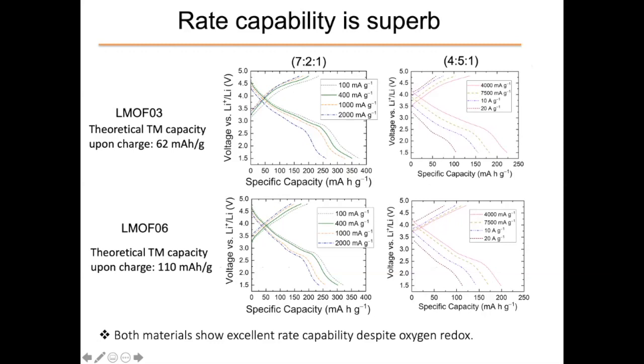But here was the sort of shocker. This is the rate capability. First, in a more normal electrode formulation, the first curve is 100 milliamperes per gram. But what you see, we can go all the way up to 2000 milliamps per gram and still get over 200 milliamperes per gram capacity. So although this is a partially disordered material, again, very high rate capability.